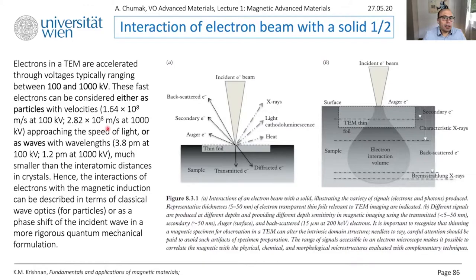It is a very, very fast electron. But at the same time, you can describe it in terms of a wave. The wavelength of this wave will be very small — in the picometer range, about 1.2 picometers. In optical techniques, the wavelength is usually the limiting factor for resolution. If light has a 500 nanometer wavelength, here as opposite you have one picometer. Therefore, you understand that the resolution of electron-based techniques is much, much higher than optical techniques.